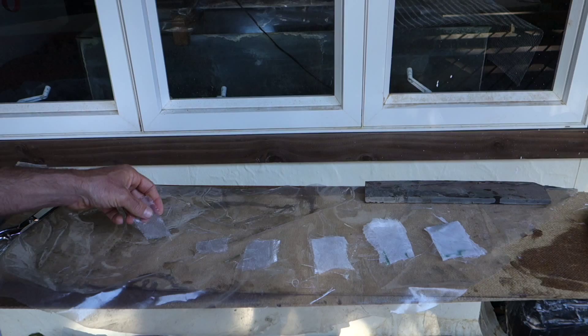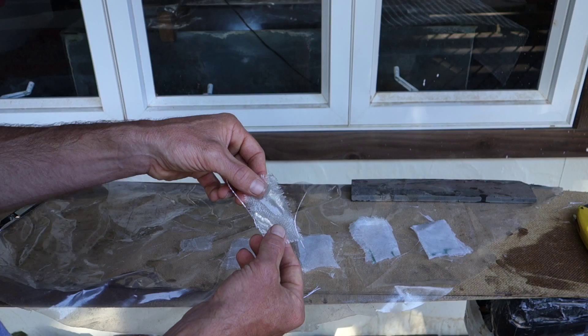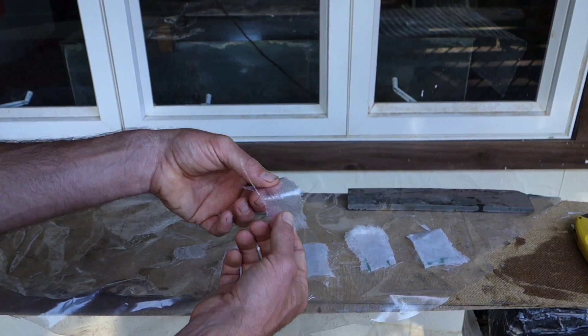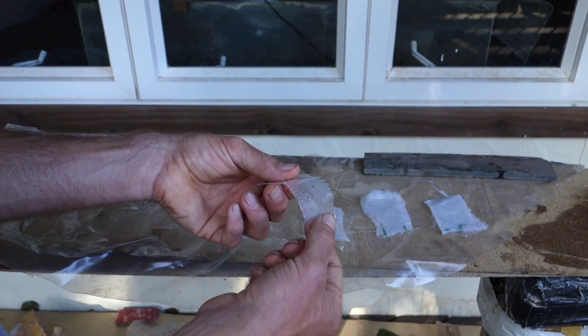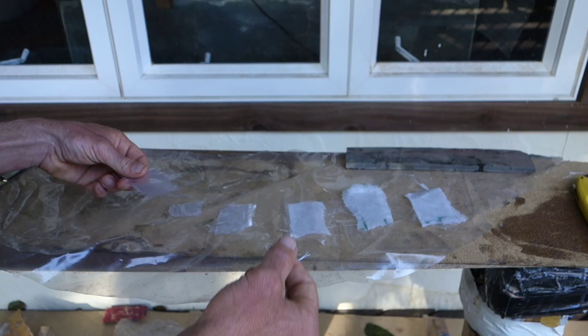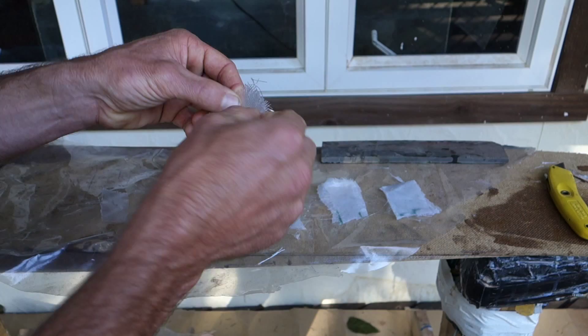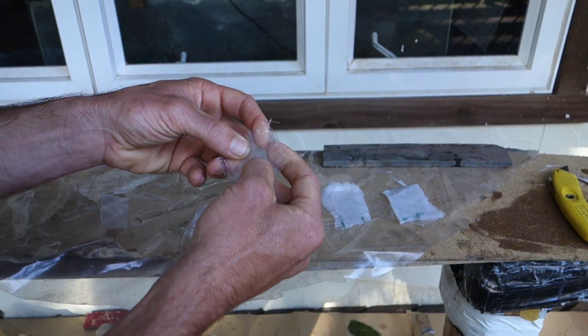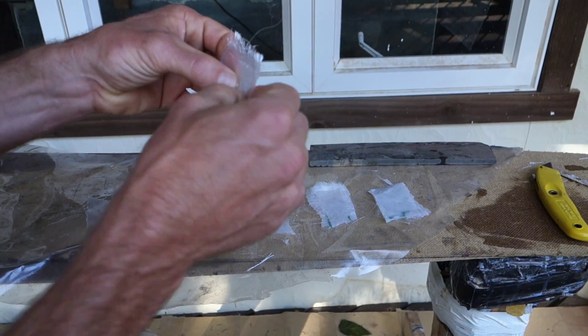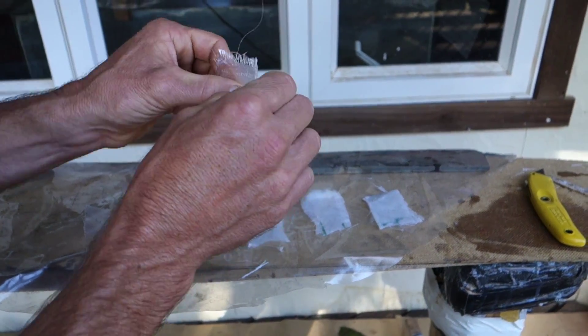See if you can catch the visual difference of the flex pattern. This is one layer of fiberglass — all glassed with Entropy Resin Epoxy. One layer is super flexy. Two fiberglass layers are much much stiffer, but still pretty flexy and feels like I could break it really easily. Three fiberglass feels about the same strength but just a little stiffer — I definitely feel like I could just snap it with no problem.